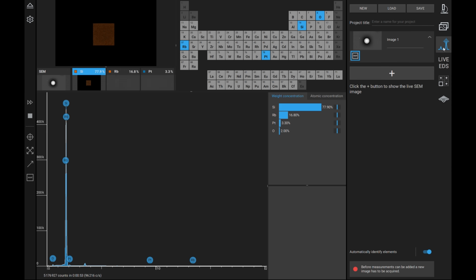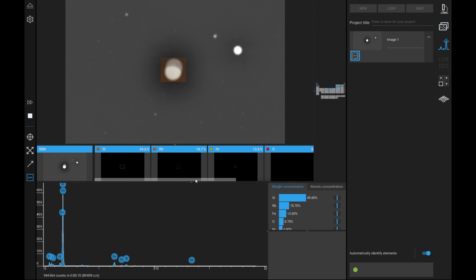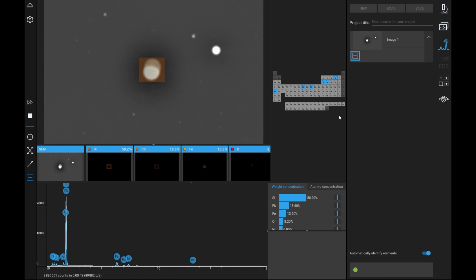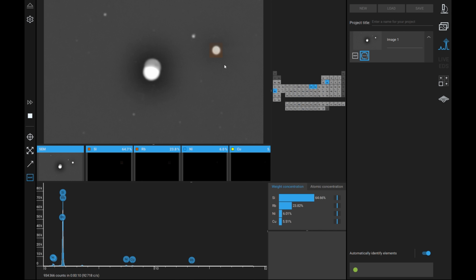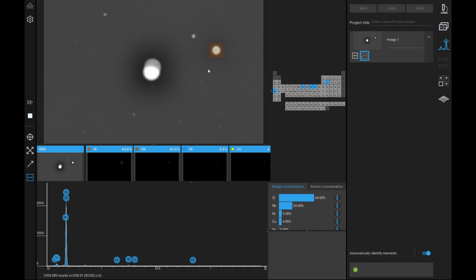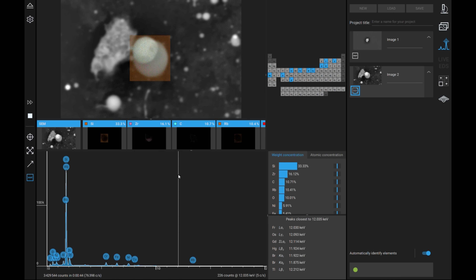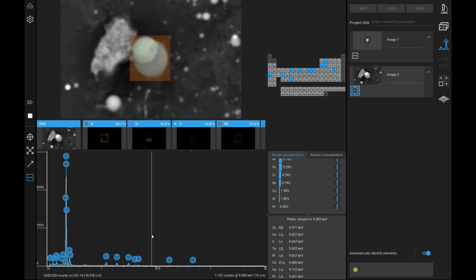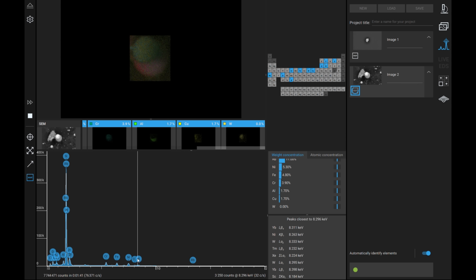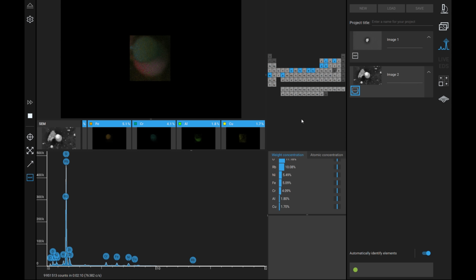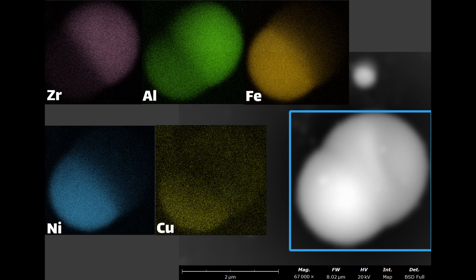The smaller the size, the better the outcome tends to be. I assume this is because the particles just quench much, much faster — there's not a lot of material, so all the molten elements are frozen in place much quicker, and it's more likely to get a good result. As we move to smaller particle size, say two to five microns, we tend to get better results. You'll still see some split or bimodal distributions, but you also start to see more even distributions of the elements.